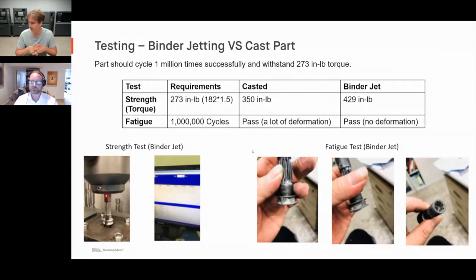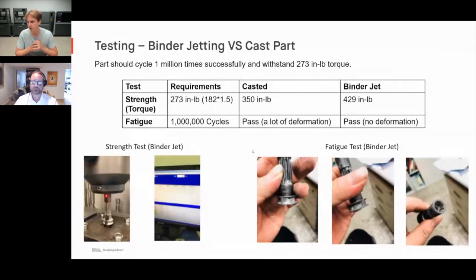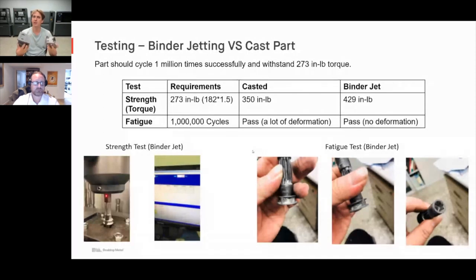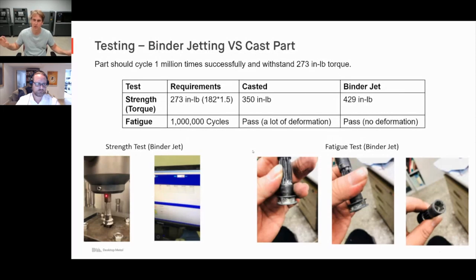Tolerances are a very common question. Where we lose tolerances is during the sintering process. We can print very precisely — controlling where the material and binder are laid down — but predicting shrinkage can be a challenge. It is very consistent, with about 20% shrinkage generally, and our software takes care of all of that for you. We're very comfortable with about 1% tolerance. If you need better than that, you can use machining or other post-processing to get critical dimensions.